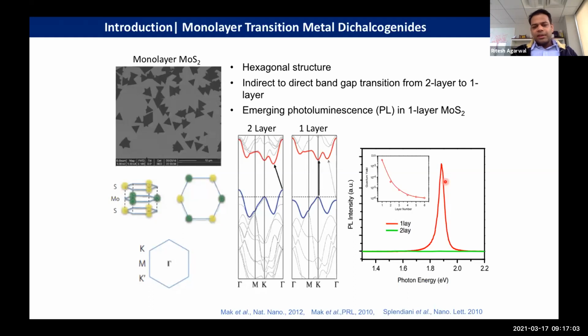So around 5 or 6 years back, how time flies, we started, there's a lot of activity in what are called two-dimensional systems, where most of the focus is on layered materials where you can peel off the material starting with graphene and then extend it to semiconductors like transition metal dichalcogenides. So you can create these planar materials which are van der Waals stacks. So you can go down to a monolayer, and in a system like MoS2 or similar systems, it was very nicely shown that these materials undergo a transition: when it's a multilayer system, it's an indirect bandgap material, but if you thin it down to a monolayer, it becomes a direct bandgap material.